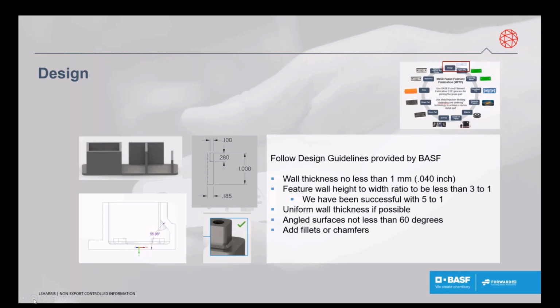We've been successful at going 5 to 1. So what that means is 3 to 1, 100 thousandths, about 300 thousandths high. We've been printing 185 thousandths wall thicknesses at an inch tall. The controlled and heated chamber seems to aid in achieving greater ratios. We started out with a chamber that wasn't heated, and we've noticed that since we have the heated chamber, we're able to increase those ratios.